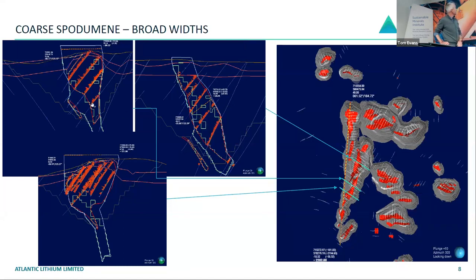Now, this is an area, obviously, that we're trying to do more studies on and try to build a system where you can actually map P1 versus P2 from multi-element geochemistry or something else, because most of this drilling is RC, and that's texture destructive, so it's hard to log grain size in your RC drill chips. And so we use diamond core, and now the guys have got their eyes in, they're actually getting better at picking up that coarse grain versus fine grain, but it's still not quantitative, it's qualitative. So that's something that we're trying to do some studies on, looking at multi-element geochem to see how we can really bed down that P2 mineralization.